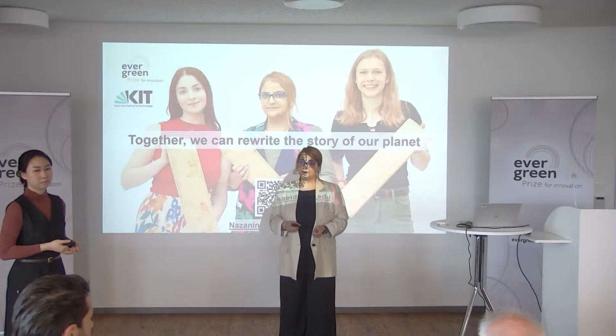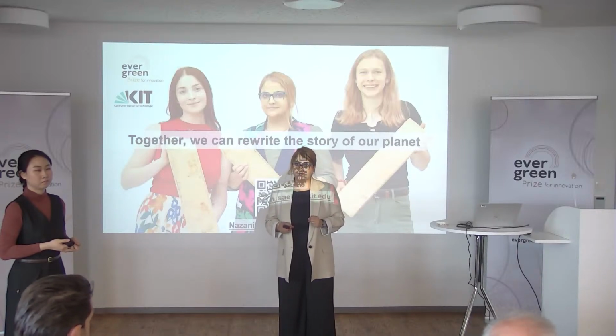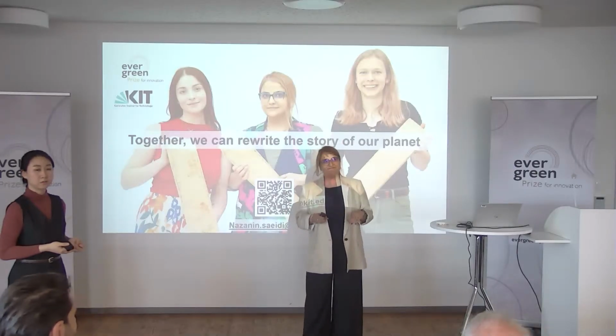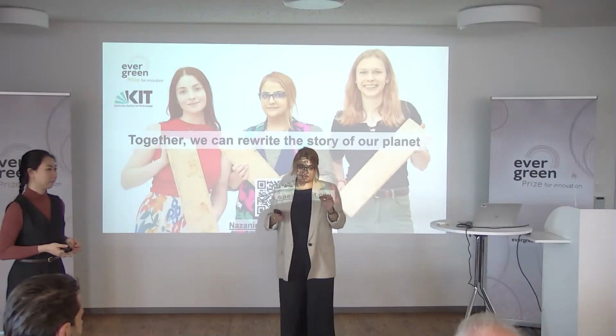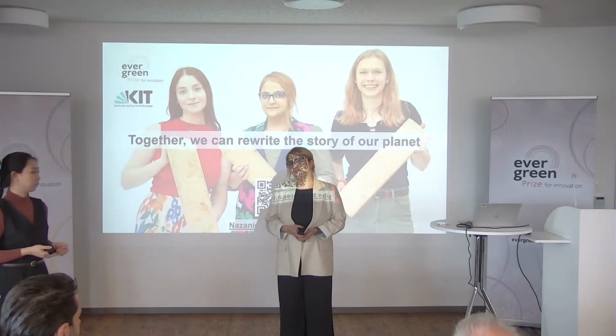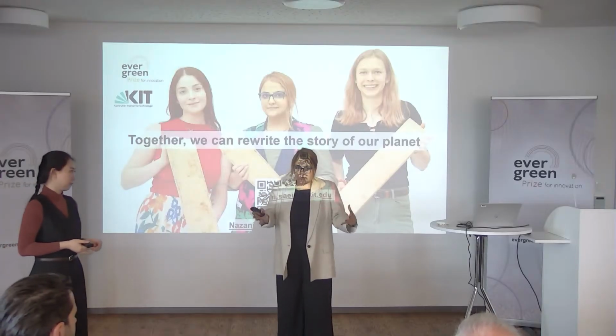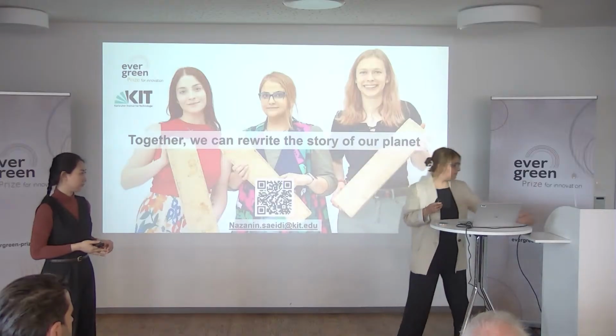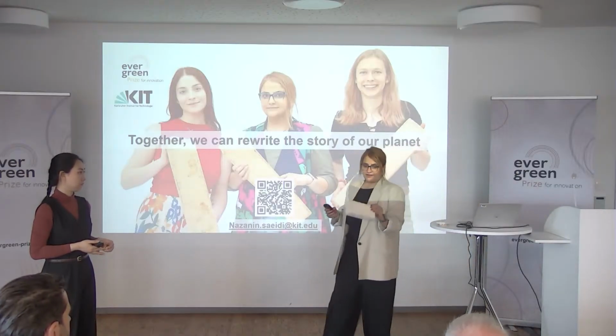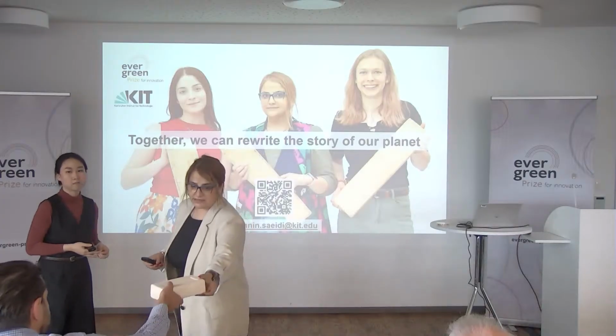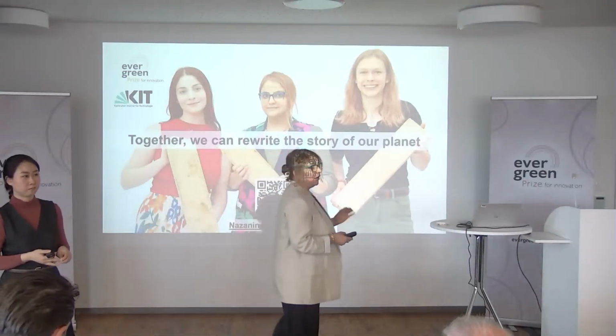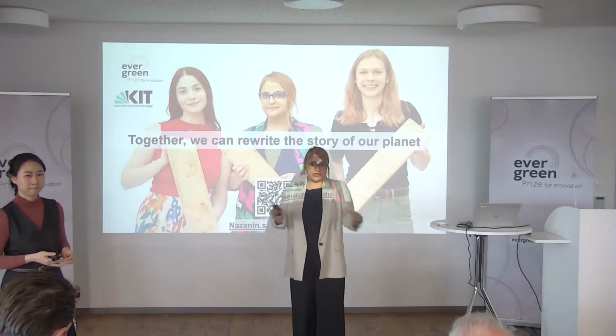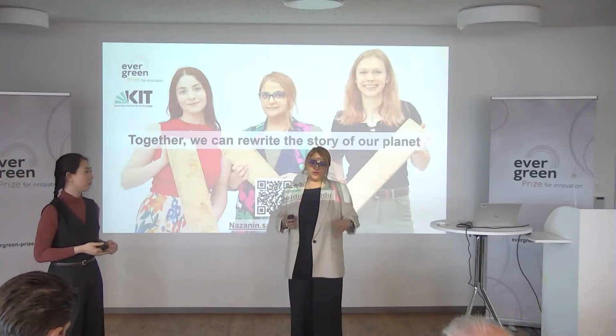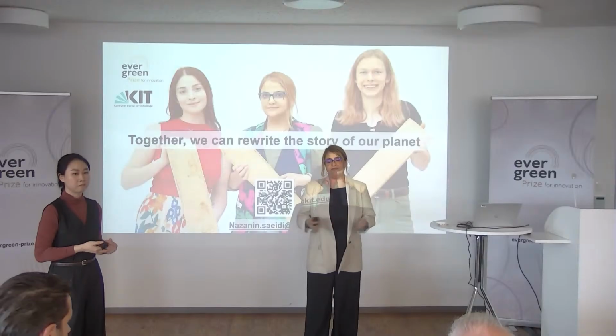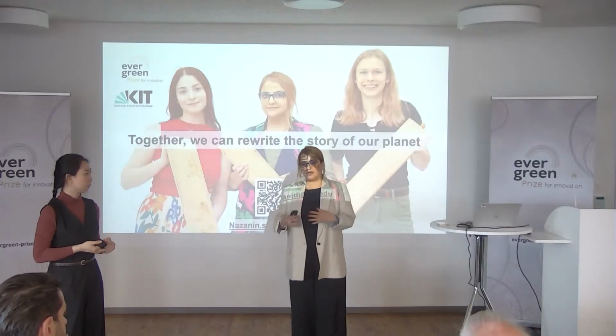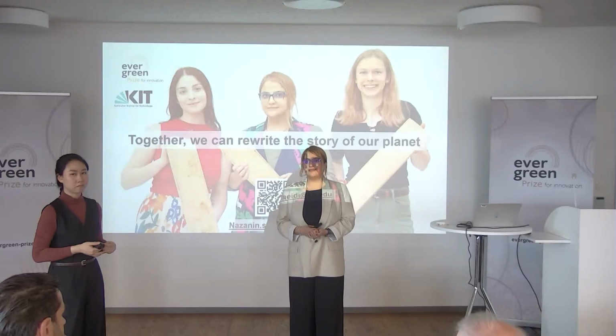Do you know the tensile strength of the mycelium fiber? Any idea? I wish I knew the exact answer, but it's not possible because everything becomes together, growing in one piece. We can't really know the density of mycelium and wood. The mycelium grows together with the wood, and we start with 1% of mycelium, but it basically occupies the whole space. But in terms of quantity, we don't really know exactly how much mycelium we have in the composite. We have tried to do some chemical analysis, but it needs funding.